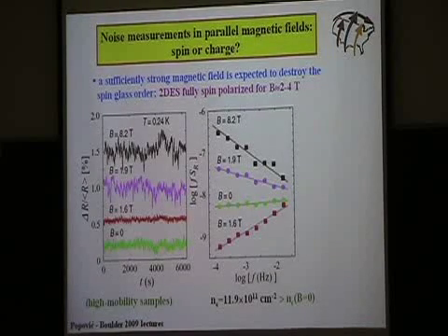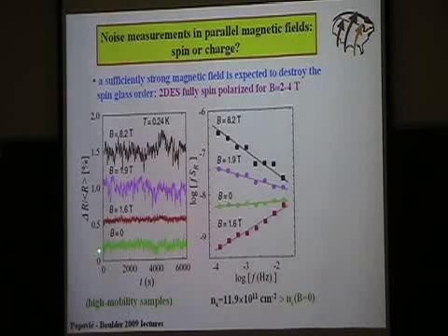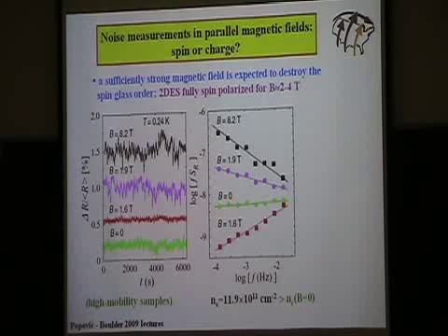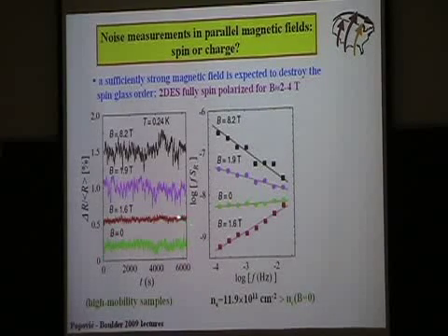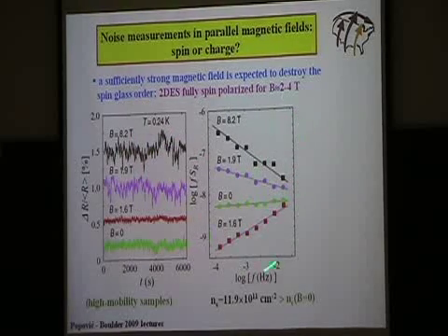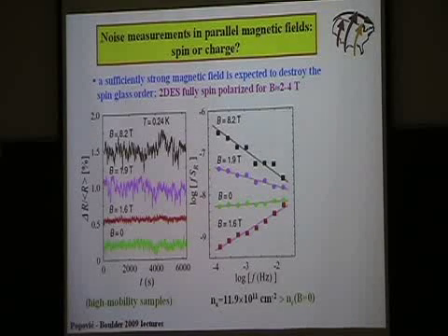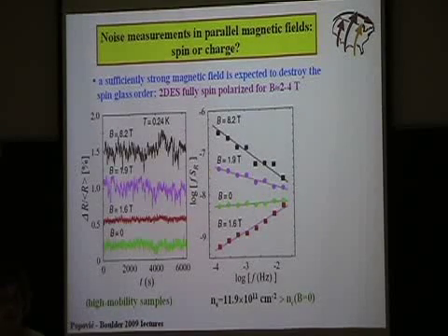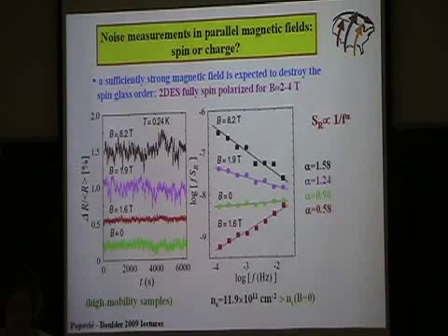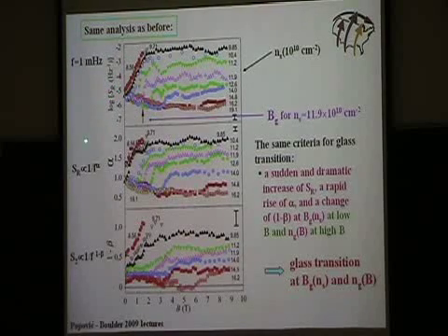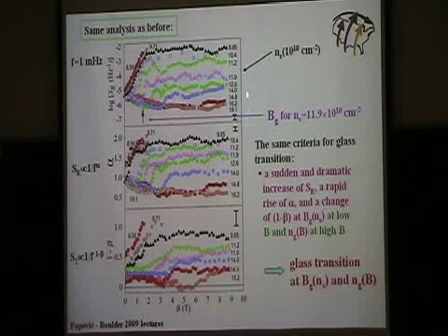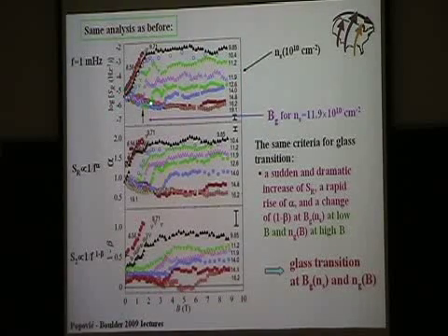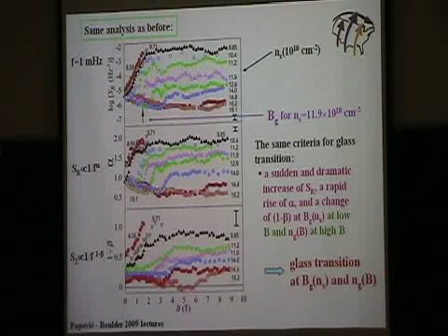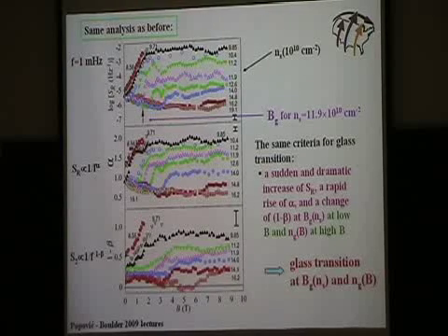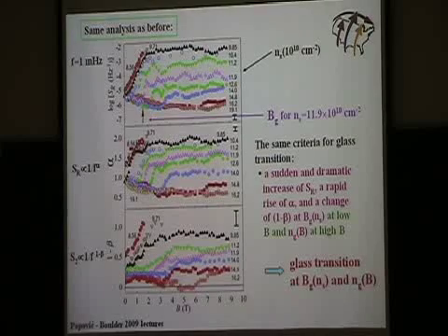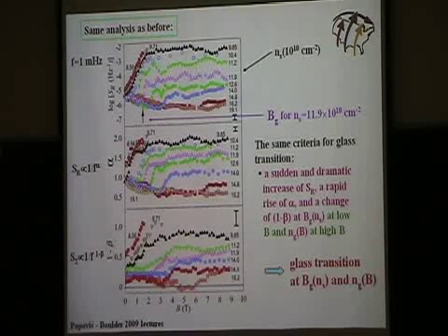So for each density, then you repeat the measurement of the noise for many different magnetic fields, and then for many different densities. So this is one example. Zero field, and you apply some fields, you can see that the noise changes, the power spectrum changes, alpha changes. So you repeat all this for lots of densities, and you repeat the same analysis. And we want to use the noise, again, as a criterion for the glass transition. In other words, we want to look at the magnitude of the noise as a function of field for different densities. So for example, for one density, when the magnitude jumps up to a high value and the exponent alpha also jumps up to a high value, the correlations also jump up, become non-zero, then we say, okay, for that density, this is the magnetic field where the glass transition takes place.